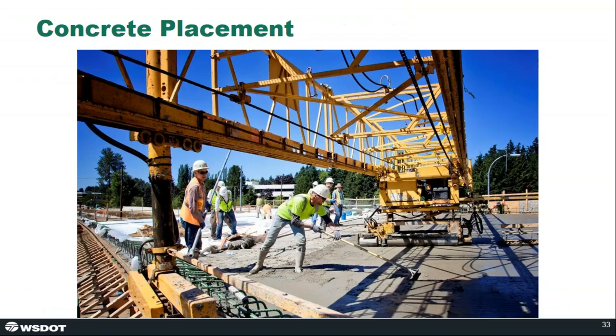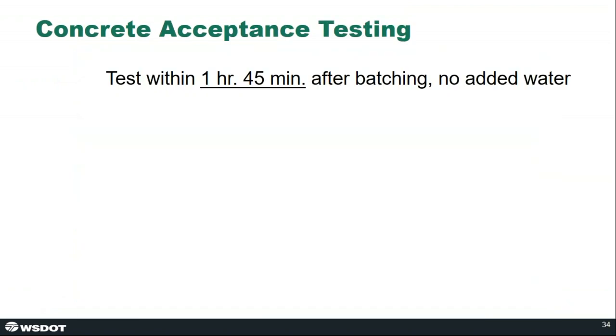Now on to concrete placement, getting to pour day. So before any significant material can be placed into the forms, we go through a round of acceptance testing, and we require that all that testing be done within an hour and 45 minutes after batching. And once the testing is complete, they can no longer add water to the mix.